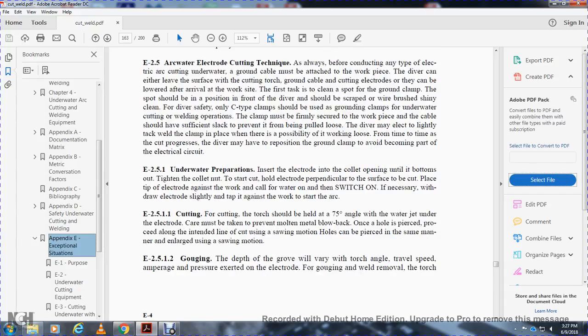2.5.1 Underwater preparations. Insert the electrode into the collet opening until the bottom. Tighten the collet nut. To start, hold the electrode perpendicular to the surface to be cut. Place the tip of the electrode in contact with the work, turn the water on, then switch on, and if necessary, draw the electrode slightly and tap it again to start the arc.